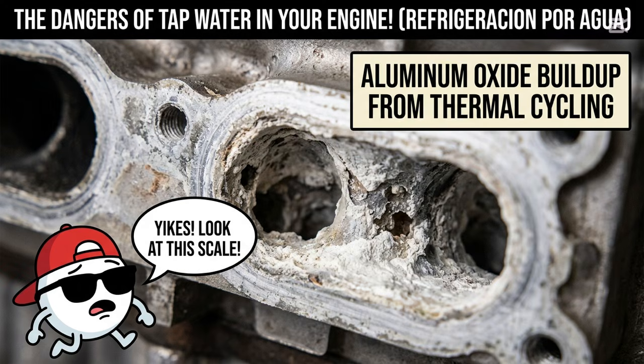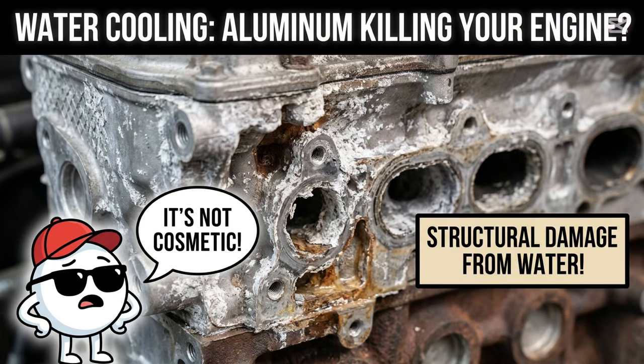Within roughly 8 to 12 hours of thermal cycling, meaning the engine heating up and cooling down through normal driving, aluminum surfaces exposed to uninhibited tap water start forming a visible layer of hydrated aluminum oxide, which shows up as a chalky white residue coating the internal passages. It's not cosmetic, that's structural aluminum being converted into oxide and washed away.